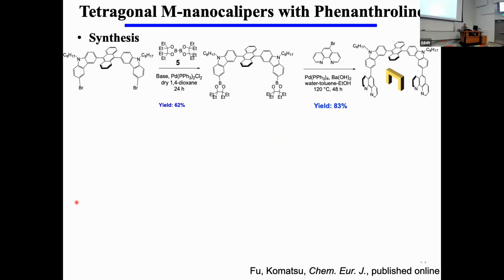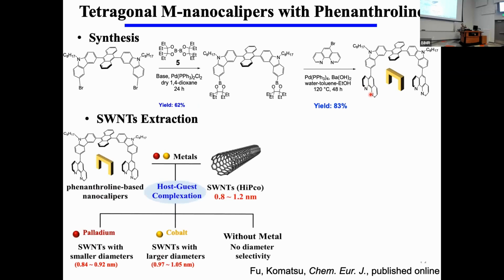And so this is the last example, quite recently published online in the Chemistry European Journal. In this case, we changed this ligand from the bipyridine to the phenanthroline. So this phenanthroline has a somewhat wider region of the pi system, which can form a more stable complex with the carbon nanotube. And in this case, we change the metals from the palladium to the cobalt, and we can tune the preference towards the diameter of the carbon nanotube.